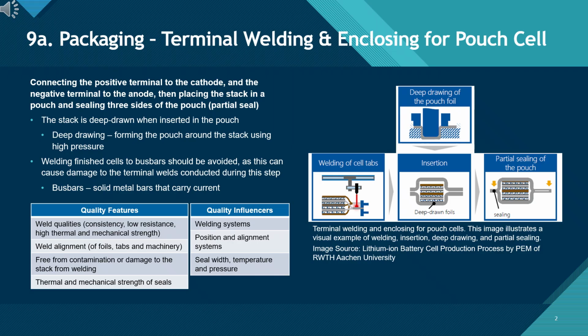later. Once the tabs are welded, the entire stack is inserted into the pouch. The pouch is then deep drawn, meaning it is shaped around the cell under high pressure, to ensure a tight, uniform fit. After insertion, 3 sides of the pouch are partially sealed, leaving one side open for electrolyte filling.